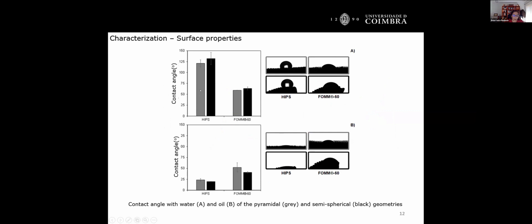And you have the contact angle with water and with oil of HIPS, both geometries. So you have pyramidal in gray and semi-spherical in black. And you have HIPS, water, oil, and foam. So HIPS is oleophilic, hydrophobic, while looking at the contact angles of foam, mainly in the pyramidal shape, you can say that it has an amphiphilic structure, okay? Because the contact angle in water and in oil is almost the same.